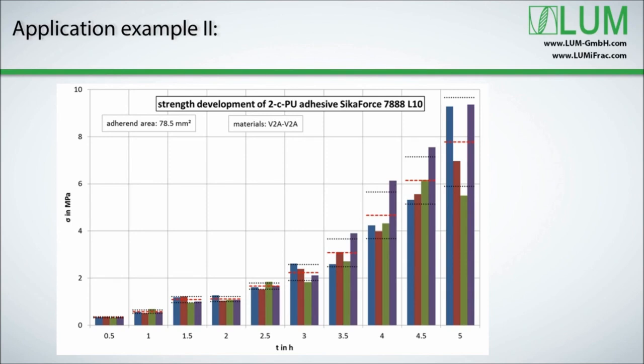As specified by the manufacturer, a handling strength of at least 2 megapascal is required. This threshold was exceeded after 3 hours of curing. During the first 2 hours of curing, bonding strength is increasing rather slowly. The remaining 3 hours of curing show a steep increase of bonding strength towards final strength. Progressive strength development was determined. For applications which require faster curing, other adhesives could be evaluated or curing conditions optimized.